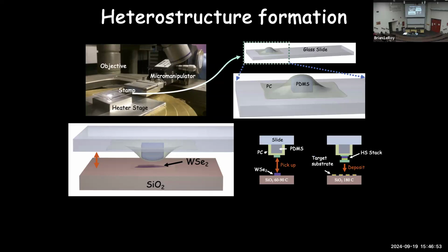And we can just repeat that process for whatever materials we're interested in putting on the stamp. In this case, we picked up something green here, probably boron nitride. Then we picked up tungsten selenide, and we continued to build some structure here. We build that entire structure, whatever we want on here, and then we can deposit it onto our final substrate by heating the stamp to an even hotter temperature such that the plastic, this polycarbonate, melts. And when that melts completely, it comes off the stamp and ends up back on our substrate.